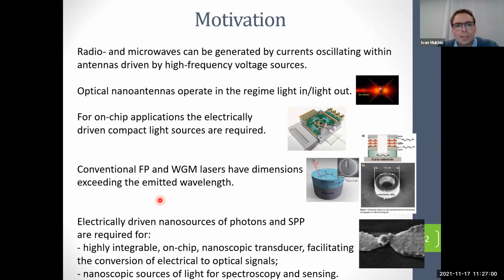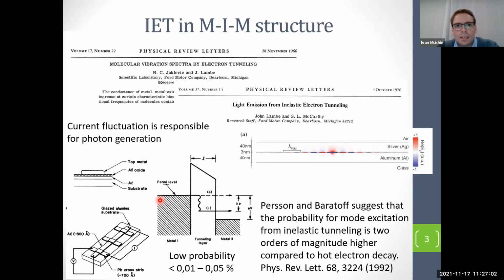It's a well-known process: inelastic electron tunneling in a metal-insulator-metal structure, which allows light generation under external voltage. The pioneering work was published more than 45 years ago by Lambe and McCarthy, and they have shown that if you have two crossed metal stripes divided by a thin layer of oxide, and if you apply external voltage to the structure, you can observe light emission.